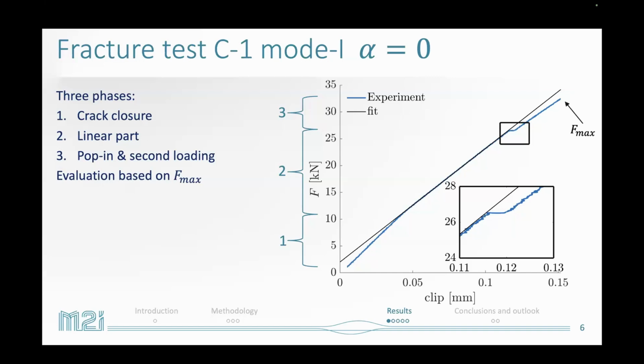And so we have an Fmax, the maximum load to fracture. In my research, I'm evaluating all these tests based on this final maximum load of fracture, not taking these pop-ins into account. That's also because we're doing mixed mode tests, and the criterion which is used, for example, the E647, is developed for mode 1 tests. In the end I want to use these to predict the failure load of real squat defects, but I will come back to that.